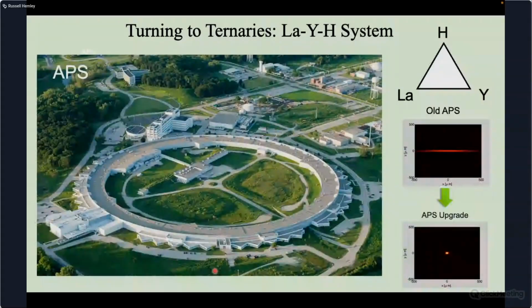So now I want to just turn to one example of a ternary system that we've looked at. These ternary systems in the hydrides have been the subject of a lot of studies over the years. I want to show this one in part also to come back to crystallography and structure work, because it shows the power of some of the newly upgraded high energy synchrotron sources. For example, the upgrade of APS, APSU, where we now have much, much tighter X-ray beams because of the change in the synchrotron lattice. And we applied this in some of the first experiments done at the APSU on this ternary, where we took some of the lanthanum out and replaced it with yttrium to try to lower the transition pressure and look at the effect of that lanthanum on the superconductivity.